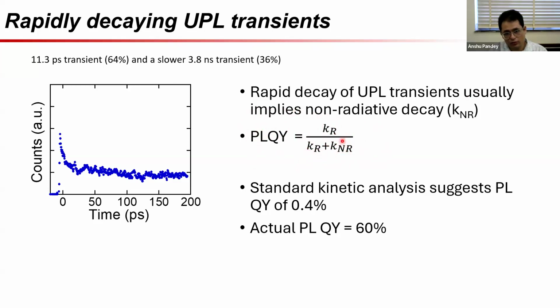KNR, what we would find, because we would say that, okay, this 11.3 and 3.8 are essentially KNRs. KR is my 300 or such like time constant, which I saw earlier. If I take this ratio, then I would actually realize that my standard kinetic analysis would pull out a quantum yield close to 0.4%. That's really, really low.